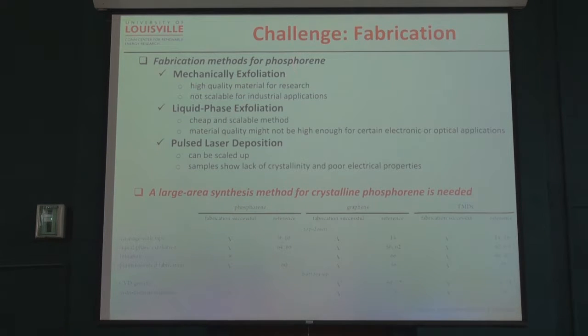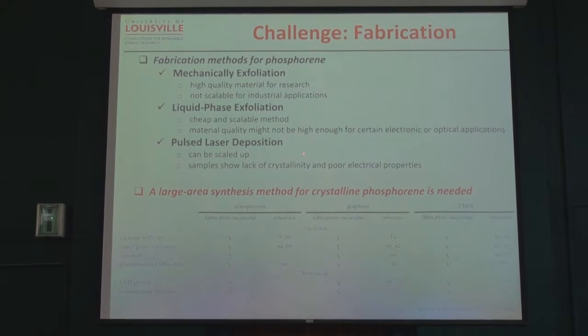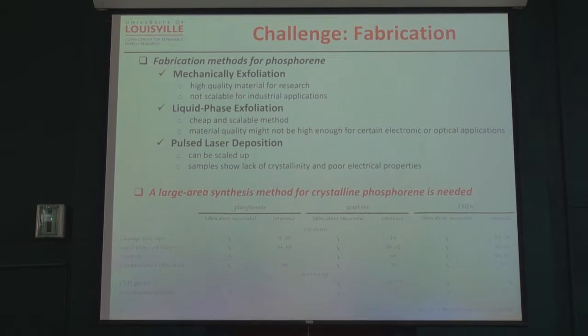That gives you very high quality material but tiny in size, right? Only 1 micron size phosphorene, so that's not scalable. But liquid phase exfoliation, where you put it in some intercalant and exfoliate, that way you can make large quantity, but the material is not very high quality because you have other defects and other disorders. Then people have also tried pulsed laser deposition. You just hit with the pulse laser, like a nanosecond or femtosecond laser, then you can deposit by this laser deposition. That also doesn't show very good crystallinity. So this is the best way to make, but small quantity. These two are high quantity but poor quality.